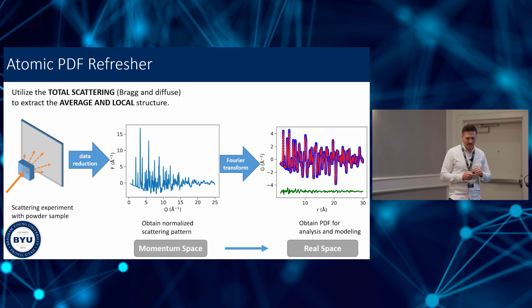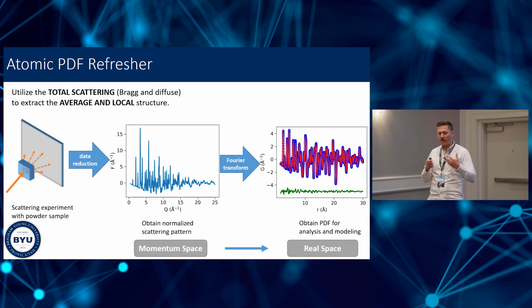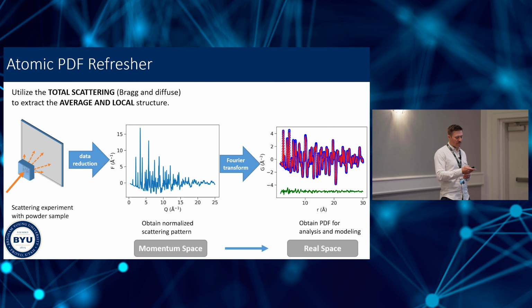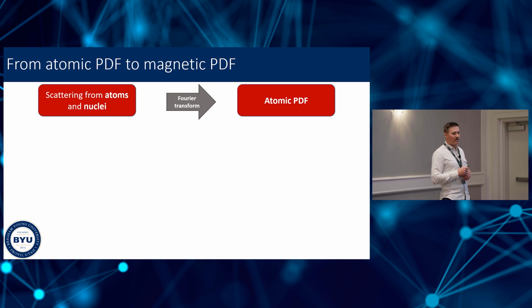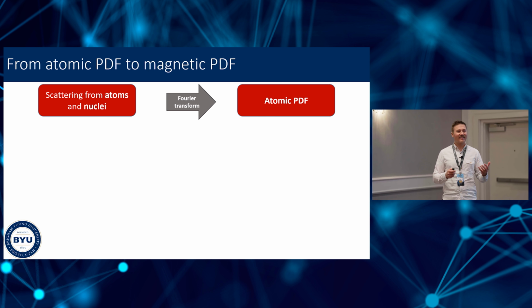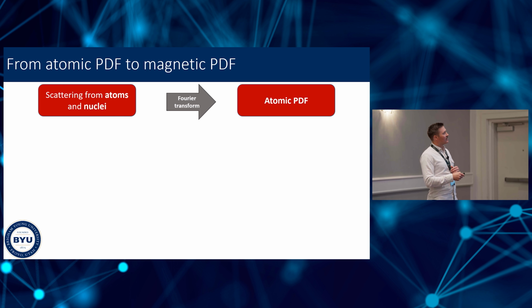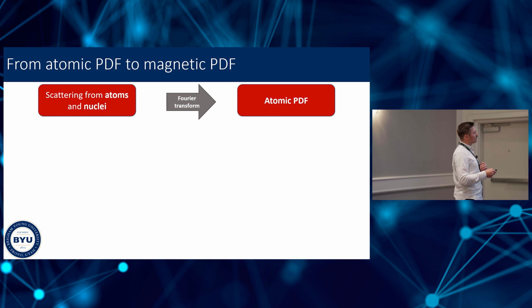So that's the atomic PDF method, which is well known, well established for looking at local atomic structure. What about magnetic PDF? Well, it's the exact same idea. So the scattering, and we're going to talk about neutron scattering today. So neutrons scattering from nuclei, you Fourier transform that scattering pattern and get the atomic PDF. On the other hand, if you just look at the intensity of neutrons being scattered from the magnetic moments present in a material and do the Fourier transform, that will give you the magnetic PDF.